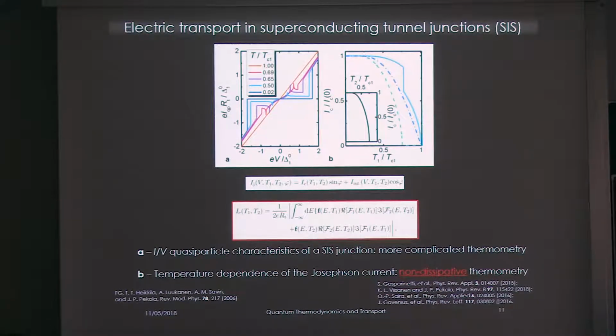And there is a second way of operation, that is the Josephson regime. So basically working at zero bias and studying the temperature behavior of the Josephson coupling. This is shown here for different configurations. At sufficiently high temperature, you see the slope is very high, so it becomes a very sensitive thermometer in superconductors. And what is nice is that a Josephson thermometer is, by definition, a non-dissipative thermometer, because it is operating at zero bias, so it's fully dissipationless thermometry. So in some sense, this can be a very useful system to perform thermometry. In this kind of research, people use both kinds of thermometry in the same structure, depending on which part we are interested in.